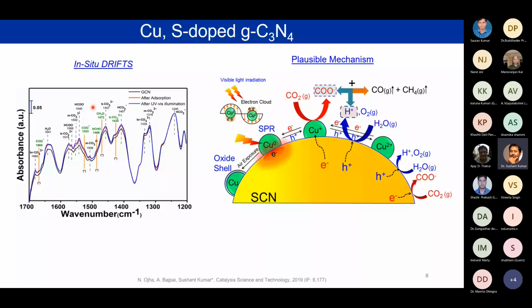Now, this is a summary of the mechanism that happens in this reaction, where one more important thing that I would like to tell you is about this copper, which we have doped. As we all know, copper is very prone to oxidation. Even when we keep copper in open atmosphere, it can form an oxide layer of 3.4 nanometer in 1 month. So that's the kind of oxide shell it will form, and it will transform to Cu2O. And then the copper no longer remains Cu0, the metallic form, which exhibits the SPR, and that's what we have chosen it for. It transforms to Cu+, and also it can transform to Cu2+, and hence these different oxidation states can interchange in the presence of the electrons and holes, and hence this could be the possible mechanism.